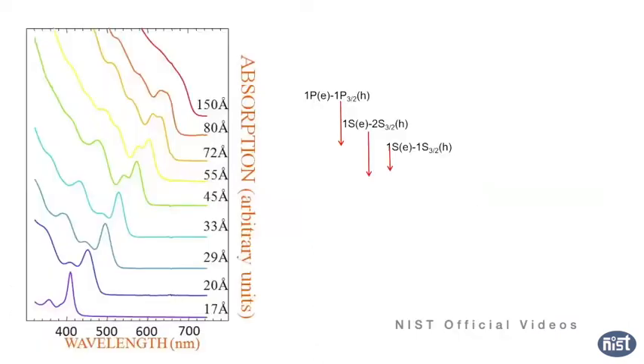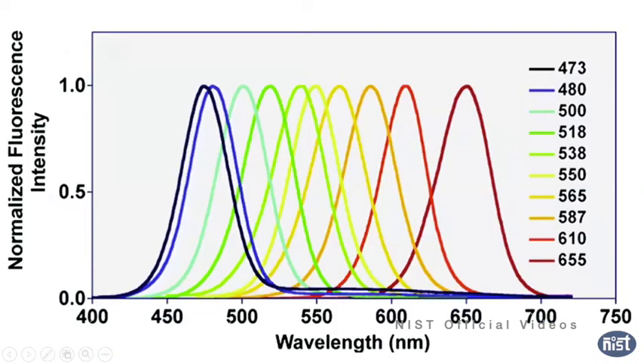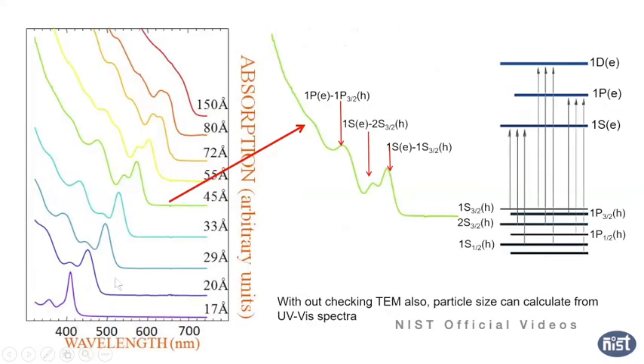So when you change the particle size, you can distinguish the different sizes of particles. You can see the absorption changes from 400 to 700 nm, which means you can get the whole visible window absorbance from the nanocrystals, and you can distinguish the different bands from the absorbance. Like this absorbance, you can see this kind of transition, 1s to 1s and others. So that's why I told you earlier, it's quantum confinement along the bands and other things.